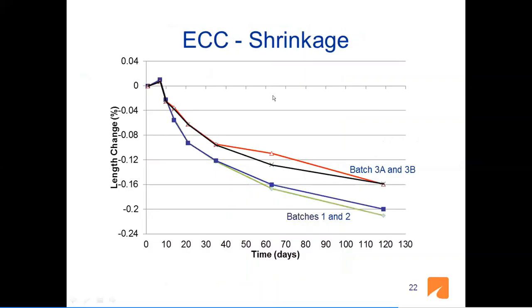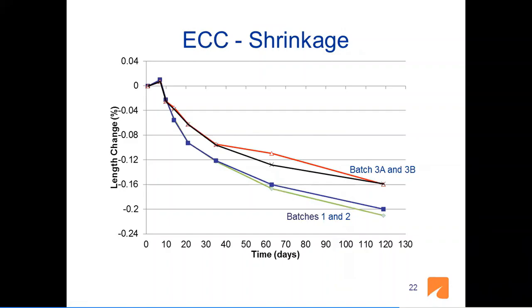Now, I'd like to show you the shrinkage values from that closure pour. We did the shrinkage testing, drying shrinkage, ASTM C157. And as you see here, length change in percent, 2,000 microstrain, 2,000 microstrain. Here it's 1,600 microstrain. These are very high numbers, like about three times what you would expect for regular bridge deck concrete. Very high numbers. But because of the fibers in the system, if it cracks, the cracks are very tight. And those cracks do not permit the solutions to penetrate into the concrete.